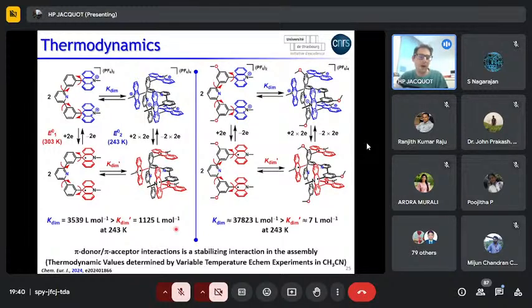And this goes well with our initial interpretation, which was that if you enrich either the pyridinium core or the spacer, you will go for the dissociation of the reduced chemical species. So that's definitively in favor of a pi-donor-pi-acceptor interaction.